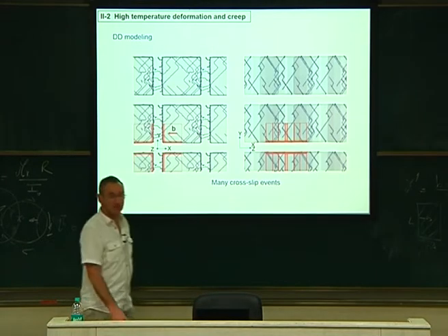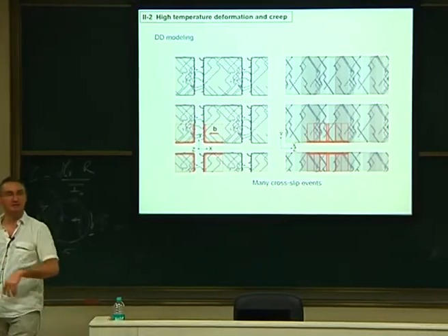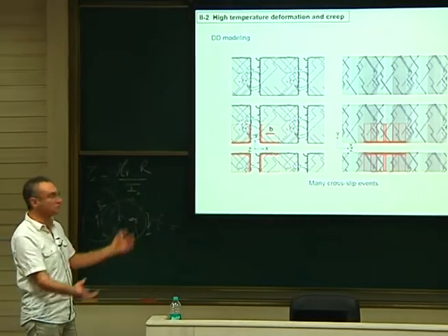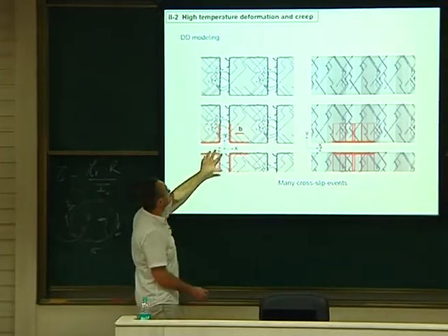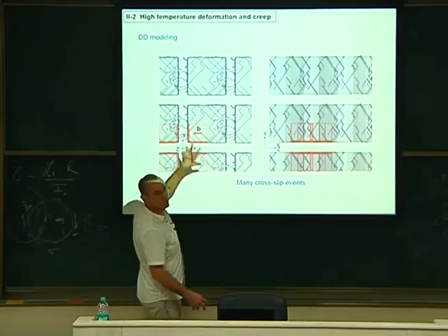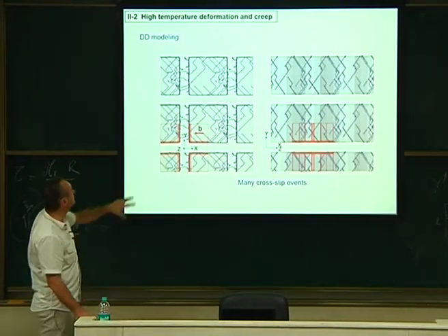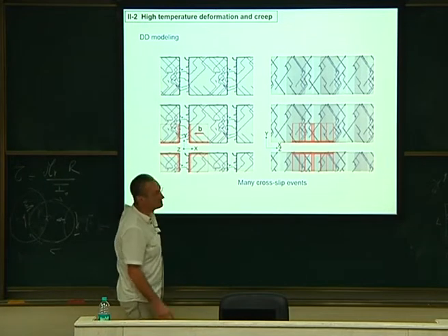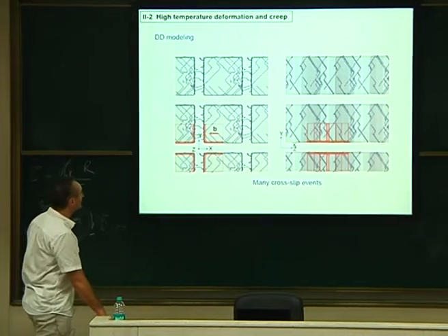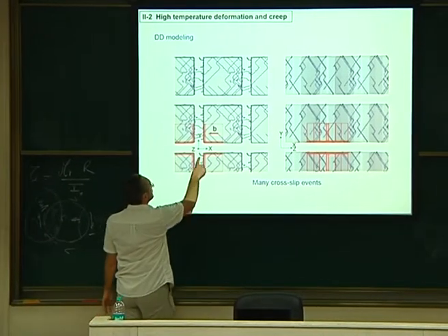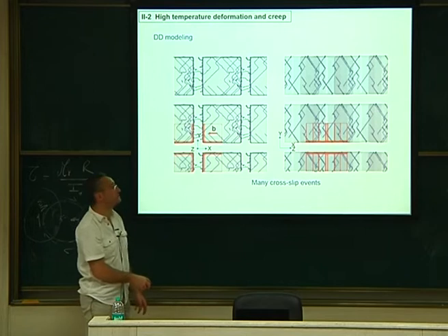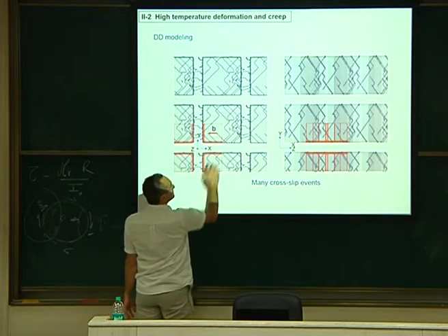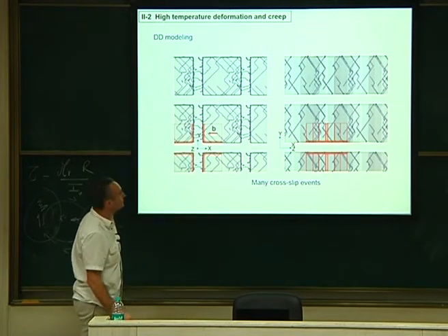Now if you look at the DD, I put dislocation sources, and I let them move in my DD code with this stress field. It's periodic, so this was my cell. I put many cells just to give a better view of what happens. But what I did was only this part. This is just replicas of the simulated volume. And you see that indeed some channels have been invaded, the P channels. Others are totally virgin of dislocations. There is no dislocation here.